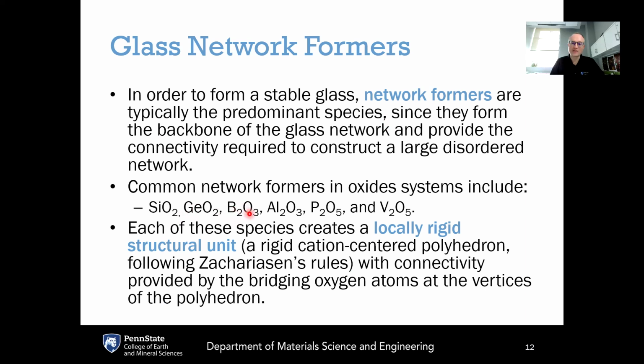B2O3, which has triangular units, and we're going to see later, can also form tetrahedral units. B2O3 forms a great glass on its own, or it can be incorporated into, say, a silicate network to form a borosilicate glass. Alumina actually requires some other chemistries in order to satisfy Zachariasen's rules, but alumina will form tetrahedral structures and can be incorporated into, say, a silica network to form aluminosilicate glasses. So this becomes part of the glass backbone. So this is also a network former.